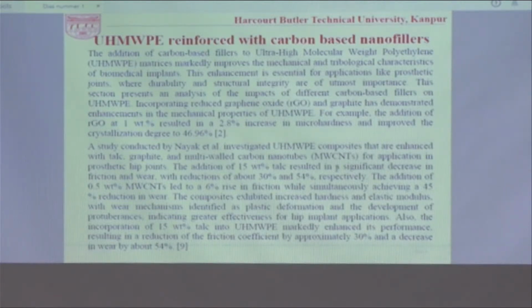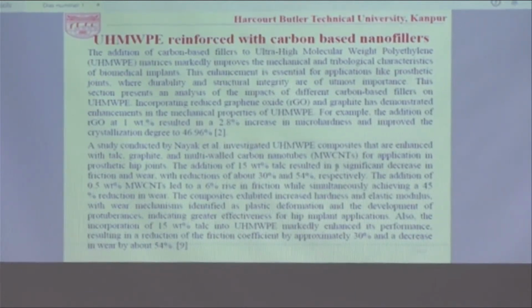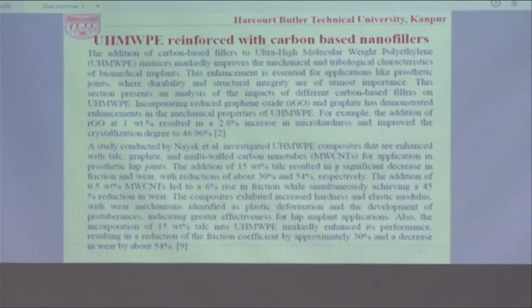The addition of carbon-based fillers to the ultra-high molecular weight polyethylene matrix improves the mechanical and tribological characteristics of biomedical implants. One of the researchers has used reduced graphene oxide and graphite for the reinforcement of UHMWPE to increase its properties, and found an enormous increase in the mechanical as well as tribological characteristics. Addition of 1 weight percent of RGO resulted in a 2.8 percent increase in the microhardness and an improved crystallization degree of 46.96%.